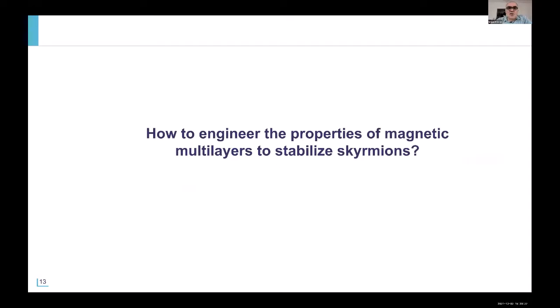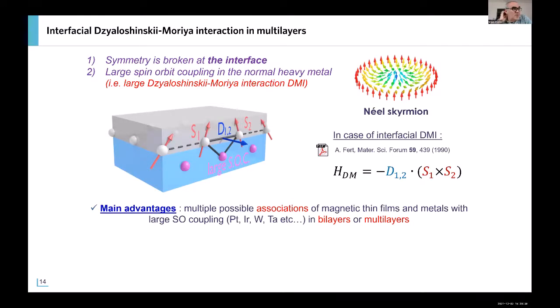Okay. So let me now say a few words on how to engineer the properties of magnetic multilayers to stabilize the Skyrmions. And this is where, in fact, we started to be very interested in this topic almost 10 years ago, because we thought that, using our expertise and experience in spintronics and in the preparation of thin films and multilayers, we could prepare a system like this with a very thin magnetic layer in contact with heavy materials in order to get these two ingredients, break of inversion symmetry and large spin orbit coupling, with the idea to stabilize Skyrmions not at low temperature and very large field, but at room temperature and, if possible, zero magnetic field or small field.